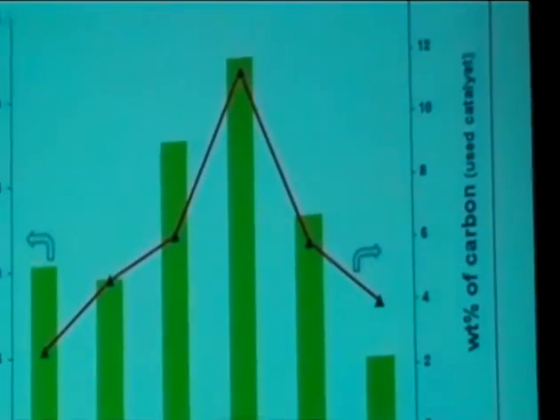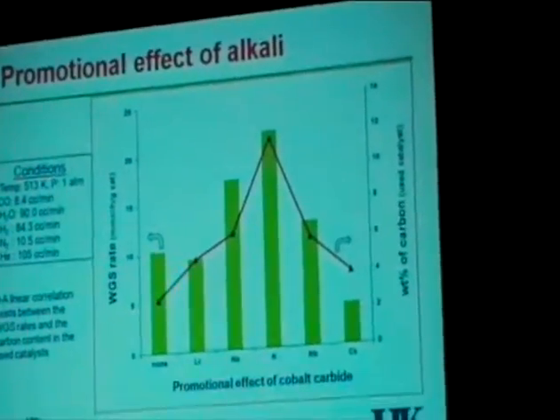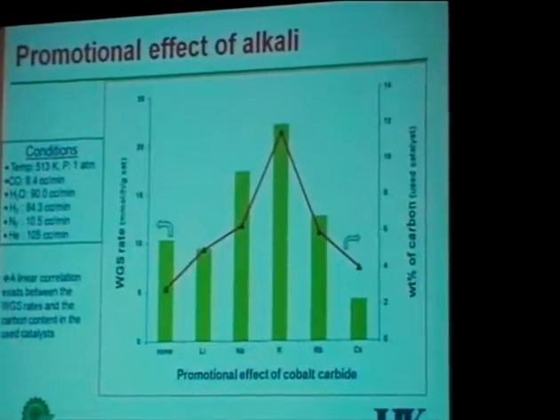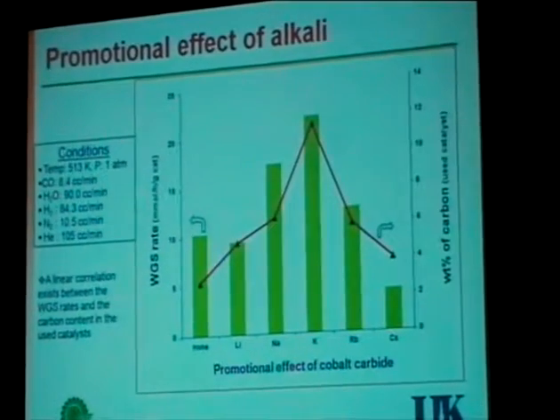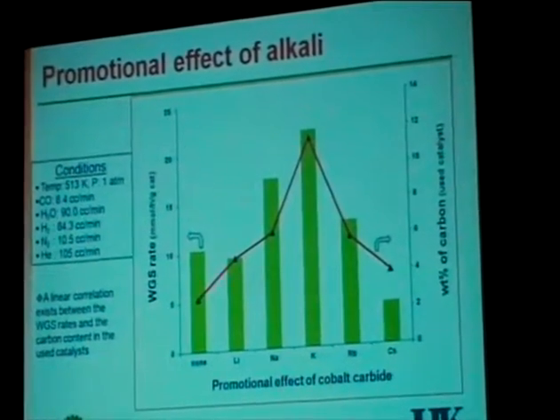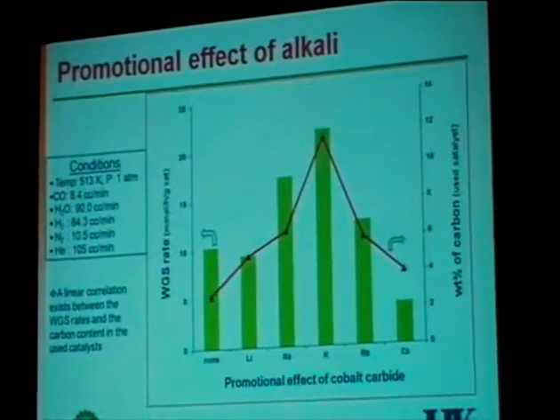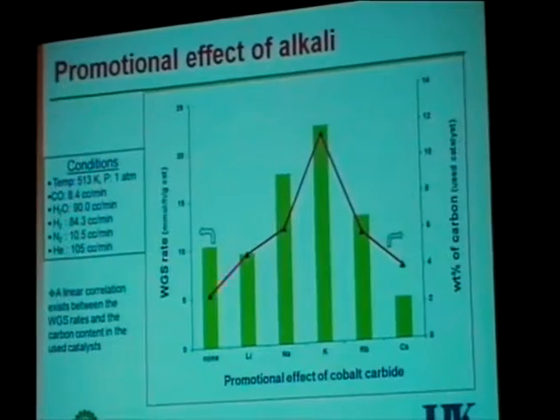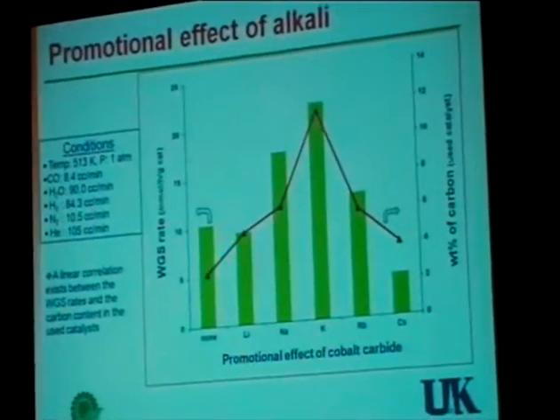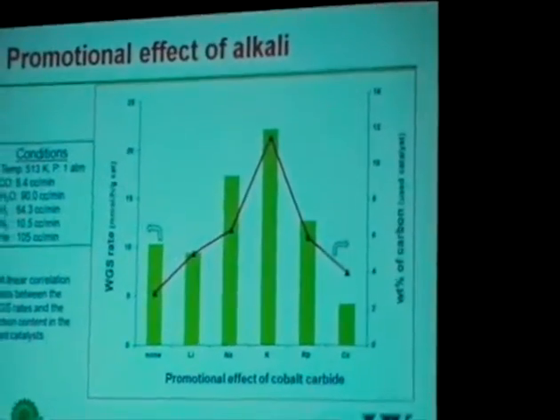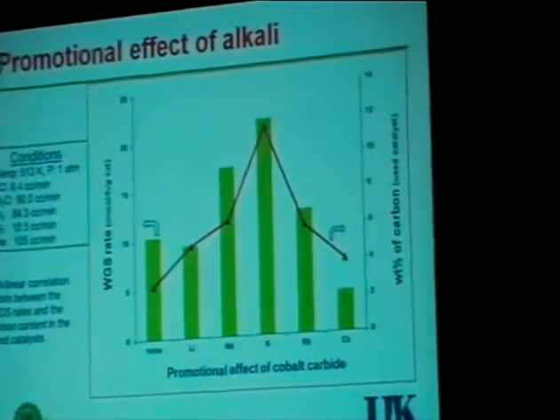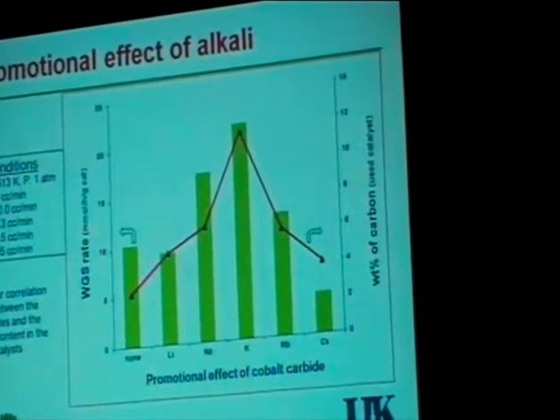catalysts. And we are plotting the weight percent of carbon in the used catalyst against the water gas shift rate observed at constant temperature, with none meaning no alkali, and with lithium, sodium, potassium, rubidium and cesium. You have the typical curve that correlates the weight percent of carbon with the water gas shift rate, which is a linear correlation. You can see that as we increase the weight percent of carbon, the water gas shift rate also increases, with the alkali series. So sodium and potassium dominate over the other alkali metals.